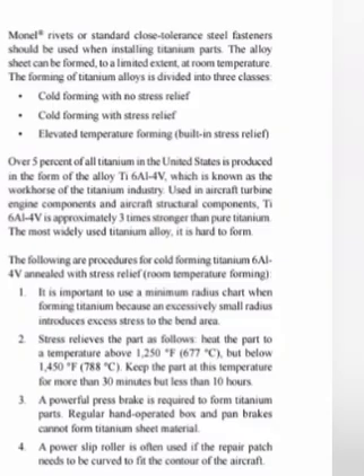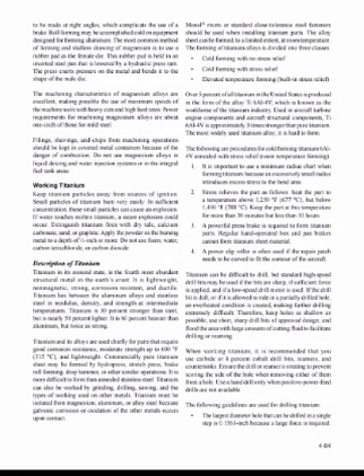Heat the part to a temperature above 1250 degrees Fahrenheit but below 1,450 degrees Fahrenheit. Keep the part at this temperature for more than 30 minutes but less than 10 hours. A powerful press brake is required to form titanium parts. Regular hand-operated box and pan brakes cannot form titanium sheet material. A power slip roller is often used if the repair patch needs to be curved to fit the contour of the aircraft.